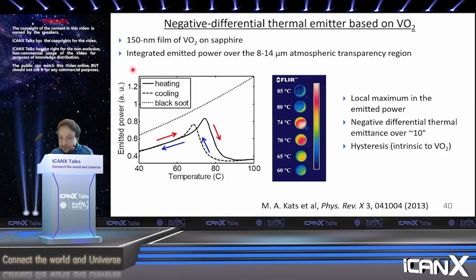So the emitted power is in arbitrary units. And before we knew all of these details of the optical properties of VO2, nevertheless we were able to get this kind of preliminary result, which is just a thin film, 150 nanometers of VO2 on a sapphire wafer. And we just measure the thermally emitted power versus temperature from the structure. And here, this is integrated over the 8 to 14 micron window where the atmosphere is typically transparent. It's a very famous long wave infrared window in infrared optics. And so the emitted power versus temperature looks like this for a black body, but has this local maximum in emitted power for the VO2 and sapphire sample, and has this region over here where the emitted power goes down with temperature. So this is quite strange, right?